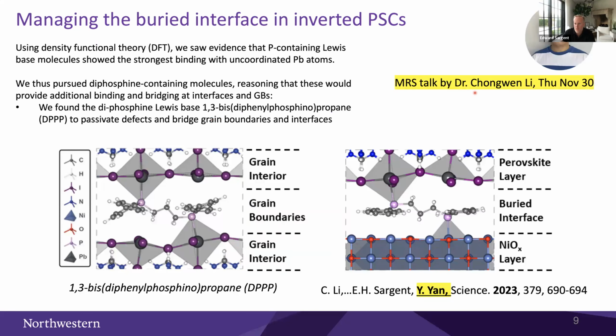So in terms of our efforts, Dr. Chongwen Li, who you'll get to meet in person this Thursday and give a little more detail on some of his projects, was really interested to see whether we could develop molecular layers to bind together the inorganic HTL with the active layer. After screening a number of candidate Lewis-based functional groups, Chongwen found that diphosphines had the potential to provide good defect passivation, but actually form a bridge between the underlying inorganic HTL and the overlying perovskite layer.